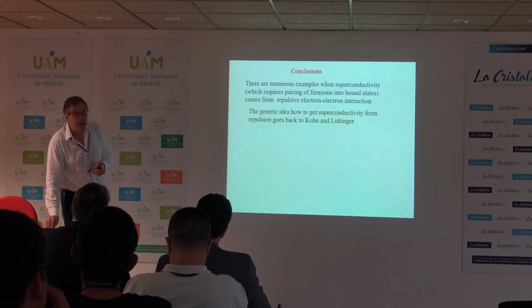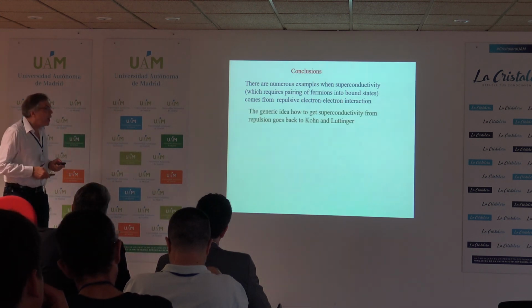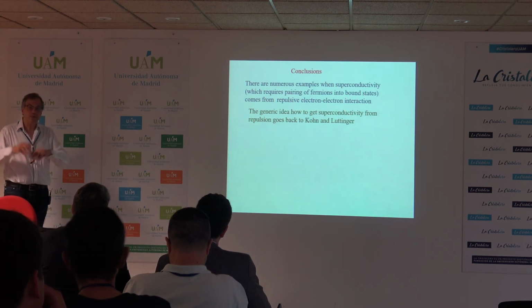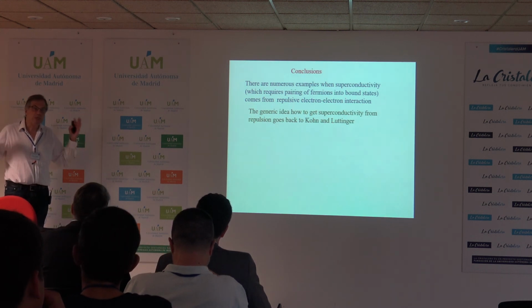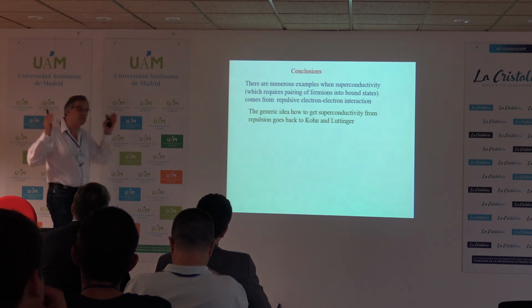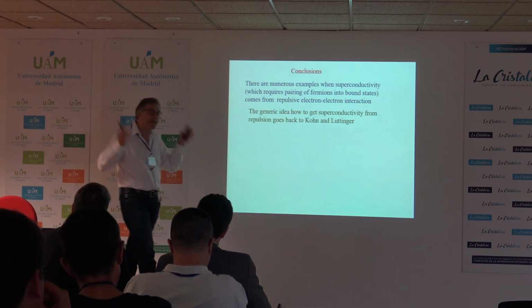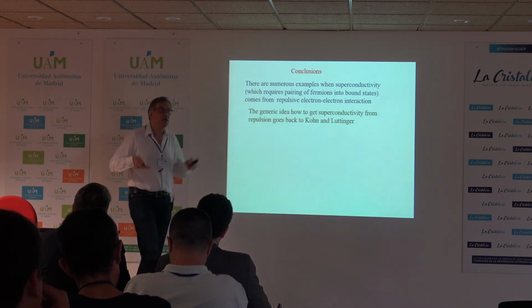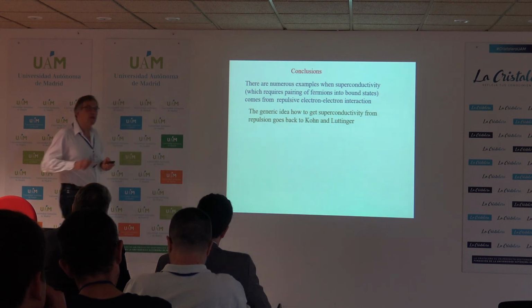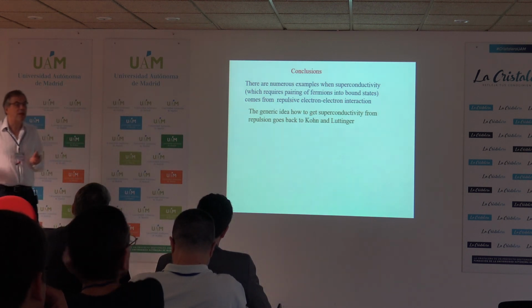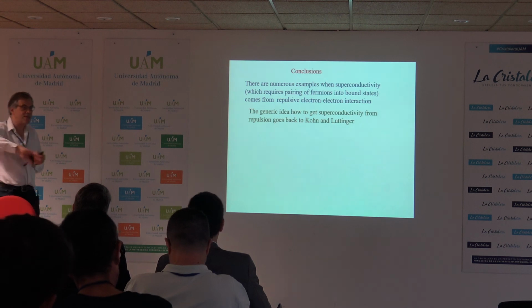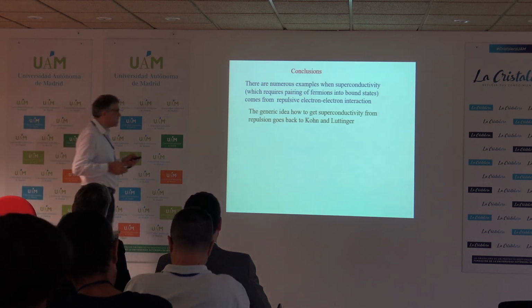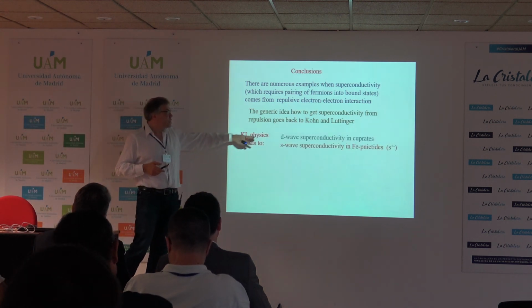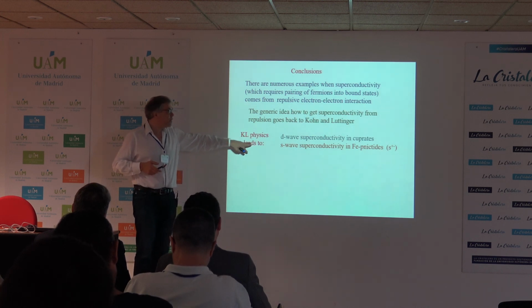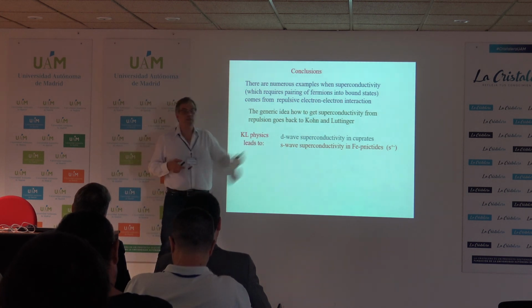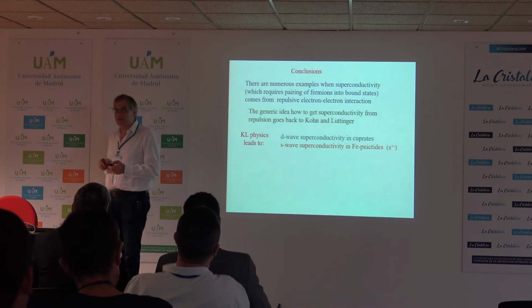General idea goes back to Kohn-Luttinger time, namely, details aside, that renormalization of interaction in the channels different from the pairing channel can change the sign of interaction in the particle-particle channel. This is now viewed mostly as interaction mediated by either spin fluctuations or charge fluctuations. You get d-wave superconductivity in cuprates, you get s+- superconductivity in iron-based superconductors.